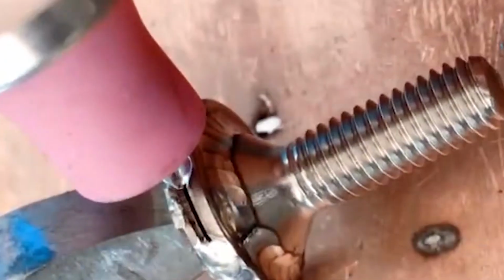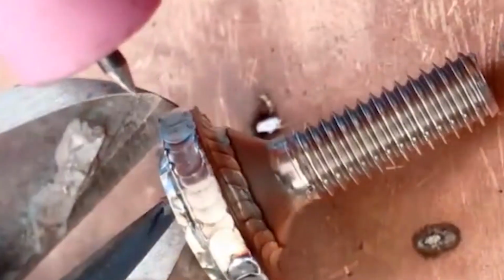2. Foundry industry: this welder also has a good performance in casting defect repair. The pores, flat holes and shrinkage holes in the casting process can be repaired quickly and accurately. It has excellent repair effect on defects such as ductile iron, gray iron, stainless steel, etc. The welding repair speed is fast, and there is no or small color difference after welding, which is suitable for the needs of factory scale production. It is recognized that the machine tool track surface, which is more difficult to repair, has also been solved ideally. 3. Repair industry of various parts and accessories: this machine can repair shafts, teeth and other parts perfectly.